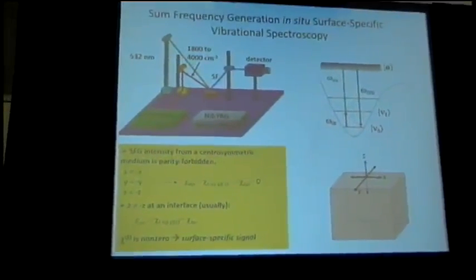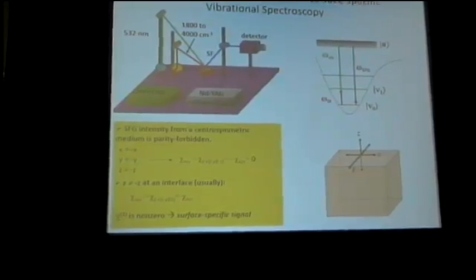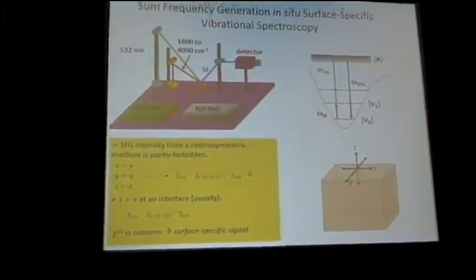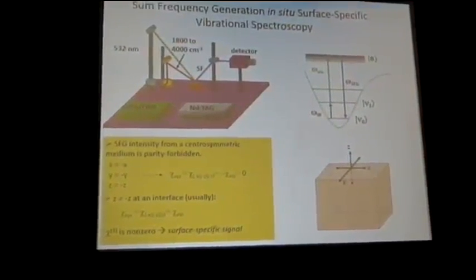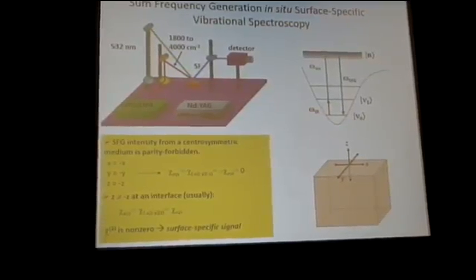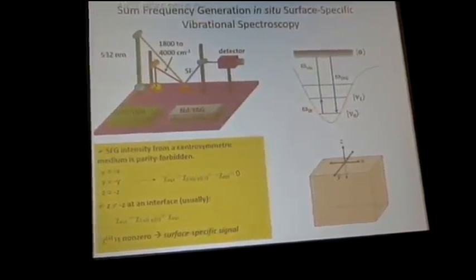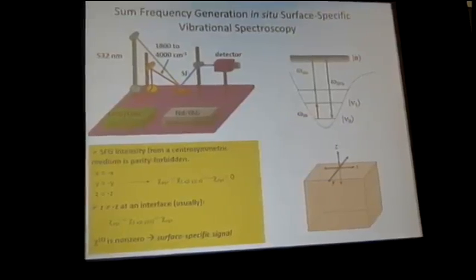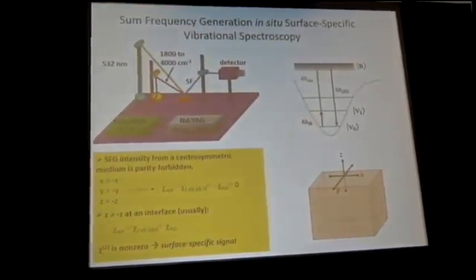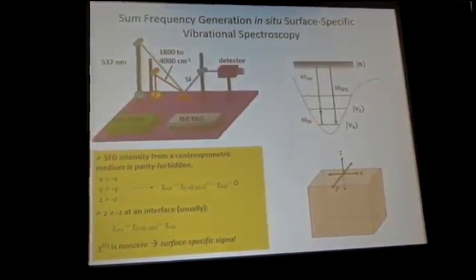So the sum frequency generation, which is two laser beams, one of them infrared, the other one visible. You keep the visible frequency constant, and you tune the infrared frequency. And this has both Raman and dipole selection rules. And the bottom line is, if you have a central symmetric environment, either a central symmetric solid or a gas or a liquid, this signal, the sum frequency signal, is zero. However, at the surface, it's non-zero because non-central symmetricity of the surface makes this sum frequency vibrational spectra alive. And so as a result, you can see reaction intermediates.